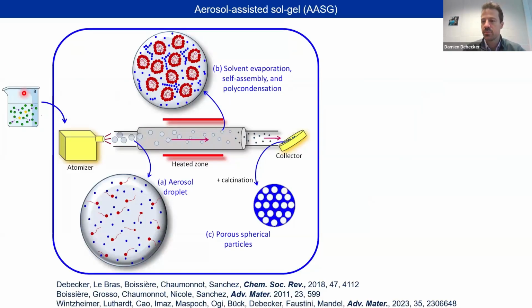So we start with the same kind of solution, just a little bit more dilute so that nothing happens here in the solution. We spray that in the form of droplets. We have a perfect control on the composition of the droplet because each droplet comes from a solution that is homogeneous. So good control on the composition. And during drying, you will have the formation of micelles, the polycondensation reactions that happen very, very quickly. And in the end, you collect your powder. You just have to calcine them.